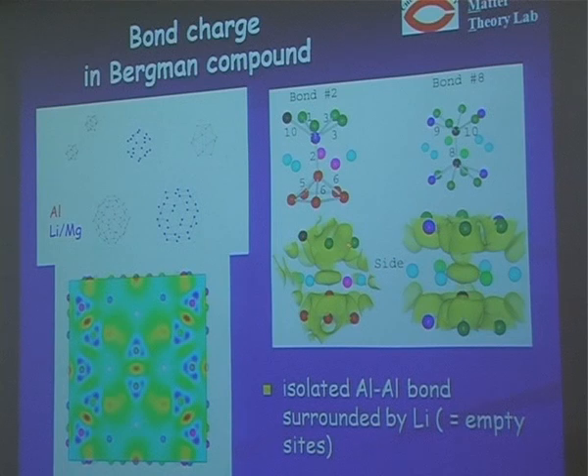So actually, if we look at the electron density map, we have some bonding charge between the aluminum atoms. Here we have two aluminum atoms, here and here, and this aluminum-aluminum bond is surrounded by 5 lithium sites. And the lithium site behaves like a vacancy. So we have a very porous structure here. And then the bonding between these aluminum atoms is enhanced. This is the characteristic electronic structure of the Bergman phase.